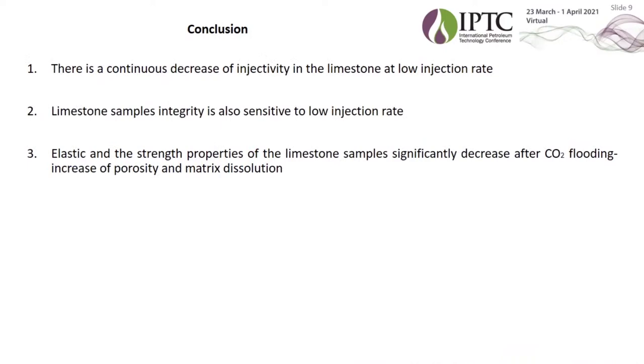In the study, limestone samples were analyzed before and after supercritical CO2 injection in terms of injectivity as well as mineralogical, petrophysical and mechanical degradation at a low injection rate. From the results obtained, we concluded that there is a continuous decrease of injectivity in the sample because of the dissolution and precipitation of the calcite in the rock matrix. We also found that limestone sample integrity appears to be sensitive to the rate of injection, because similar interaction and loss of matrix integrity were reported in earlier studies in which a high injection rate of CO2 was used. Elastic and strength properties of the sample were also decreased after injection because of the increase of porosity and matrix dissolution.